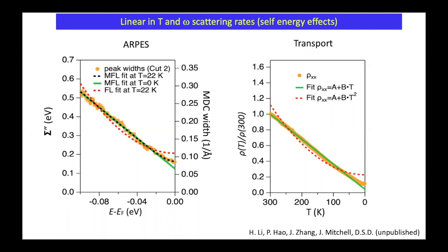Okay, so sort of a linear thing here, and quadratic-like if you like, but really just marginal Fermi liquid all the way. And here's transport data, normalized resistance versus temperature. Now, this is versus frequency, this is for temperature. It's not really arbitrary because I know how to connect them with this beta term, roughly pi. A T squared on this scale is roughly omega squared on this scale. So roughly the same. And again, I just compare the quadratic and the linear, and you can see the scattering rates are quite similar between them.